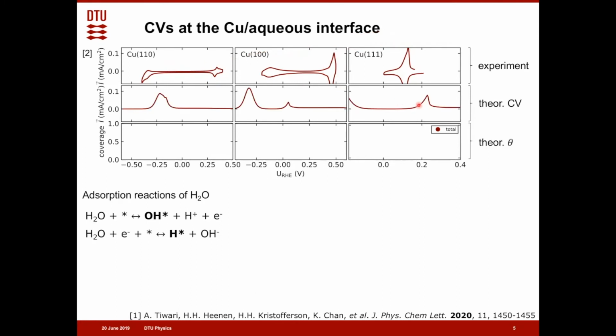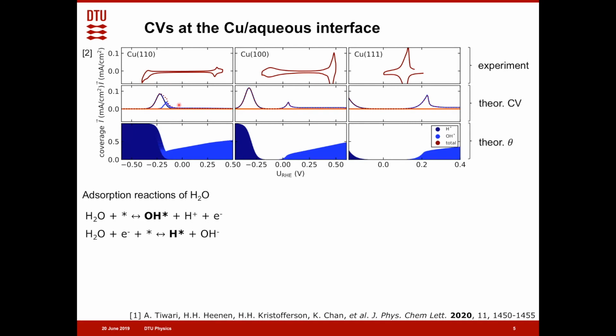The simulated CVs look rather different than what we expect. First of all, we find in some of them 2 signals instead of 1 signal, and the area under the peaks is larger than what we find in the experimental spectra. Since we perform simulations, we can relate these features to the specific adsorbates as shown in the bottom panel.